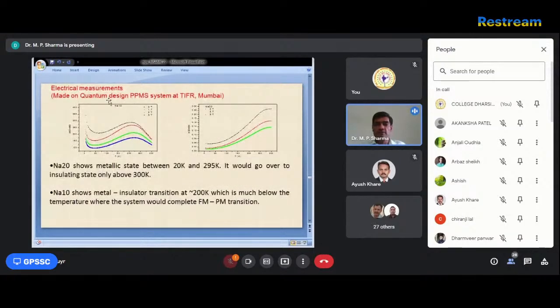Now we have to take another measurement, an electrical measurement, which is made at TIFR Mumbai. So this is for sodium 0.1 and another is 0.2 at different fields. One is 0 Tesla, 1 Tesla, 5 Tesla and 9 Tesla that we have taken. So when you increase the field, the resistivity is decreasing. So we can say there is some magnetoresistance.